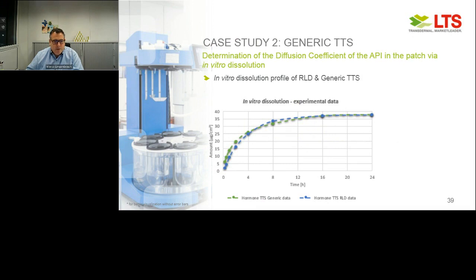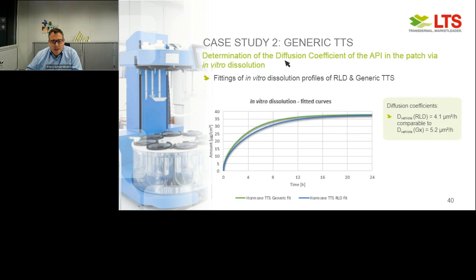In the first step, when we develop a generic formulation, one of the first steps is looking at the dissolution profile and the drug release, in this case within 24 hours. Here we compare the blue curve, the reference listed drug, to a generic formulation. The drug release is done within 24 hours, until it's completely released. Then we take those data, put them into our software, and fit those curves. By that, we can determine the diffusion coefficients of the API within the patch. And we see pretty comparable results of this diffusion coefficient when we compare these two formulations.